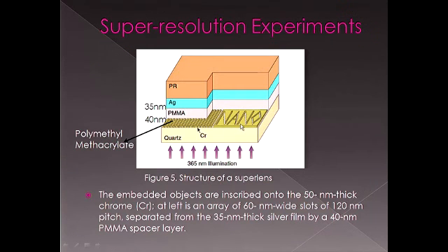So here is, as far as I know, the first experiment to show super resolution by using a superlens. Here is what they did. This is a mask made of chrome, and after that there is PMMA, a transparent material which is 40 nanometers thick. After that there is a layer of silver which is 35 nanometers. This layer of silver works as a superlens, and it will transfer the pattern on the mask into the photoresist.